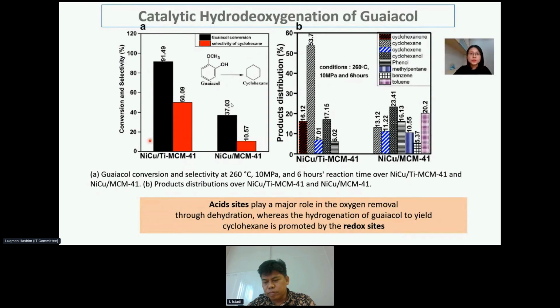Based on the results, it indicates that the titanium-doped MCM41 catalyst renders the highest guaiacol conversion as well as cyclohexane selectivity. And when we look at the product distributions here, it indicates that the modified catalyst renders a much more selective reaction pathway as compared to the pure MCM41-based catalyzed process.